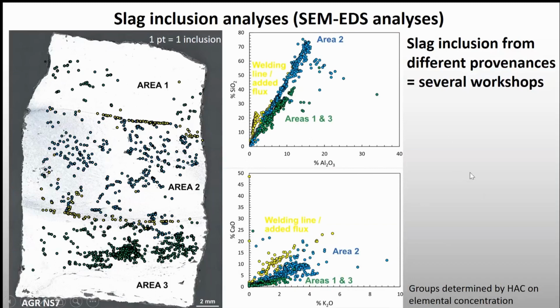calcium oxide, potash also, which clearly shows that first, here on the lines, the yellow inclusions here, they're due to addings, which were flux, which was added during forging, maybe a bit richer in calcium and in silica, flux, which is usually added to prevent the metal from burning, from oxidizing too much when it's a hot forge, especially for welding, and you have to reach some really high temperatures.